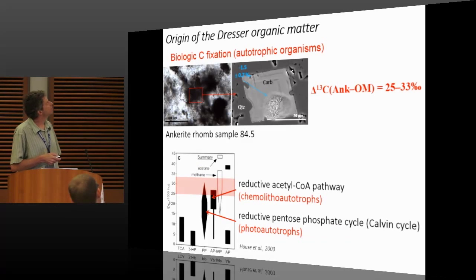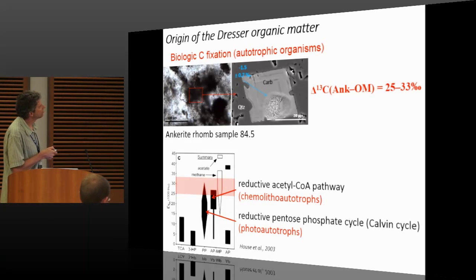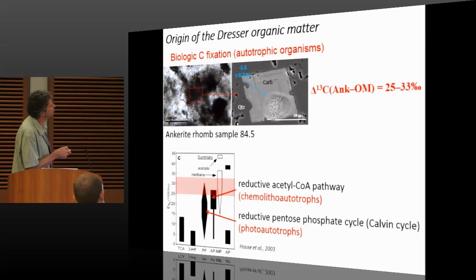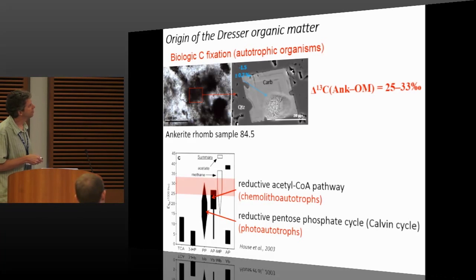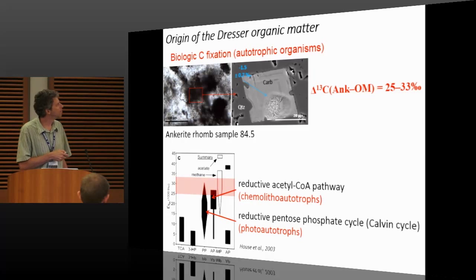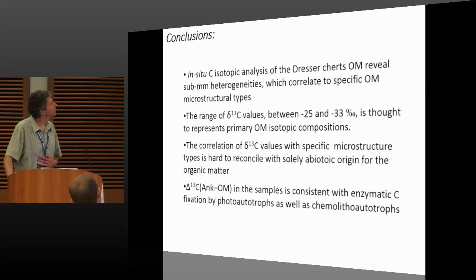And how does our data reconcile with a biogenic origin? In some of the samples studied, we have also measured the isotopic composition of ankerite carbonate rhombs, and we have found that isotopic fractionation between ankerite, which is the inorganic carbon, and organic matter is in the range of 25 to 33 per mil. And this range is consistent with carbon fixation both by autotrophic organisms using the reductive acetyl-CoA pathway, which are mostly chemoautotrophs, and organisms that utilize the Calvin cycle. So our data cannot distinguish between these two carbon fixation paths, but it is generally consistent with autotrophic microbial carbon fixation.